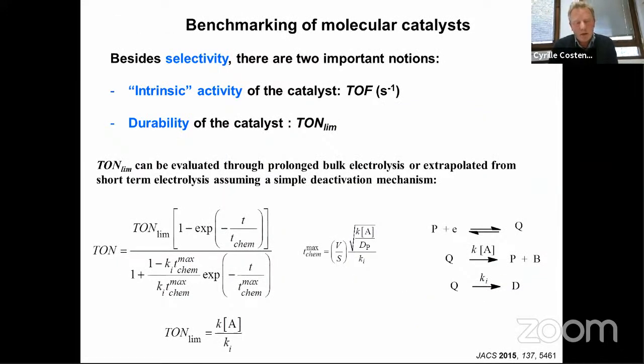Now, let's say you are interested in a specific reaction and you would like to compare different molecular catalysts. Of course, you have different benchmarking parameters. One is the selectivity. If you compare different catalysts, you have to know whether each catalyst gives the same selectivity if you're looking at a reaction that gives different products. Another parameter that I will discuss later on is the intrinsic activity, the turnover frequency, that, as you can expect, depends on the rate constant for the reduction of your substrate by the electrogenerated catalyst. Then there is a third important parameter, which is the durability of the catalyst that you can characterize by the maximal or limited turnover number.